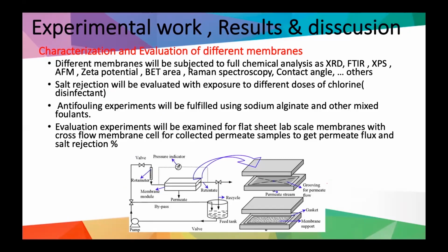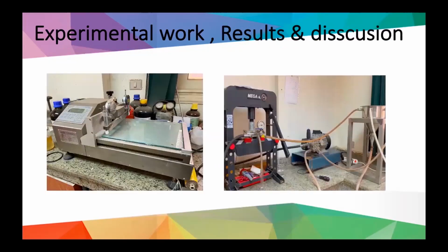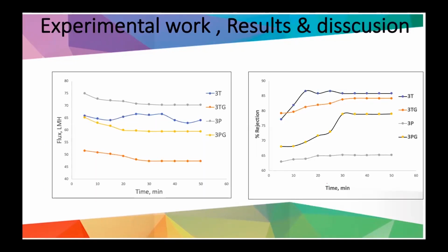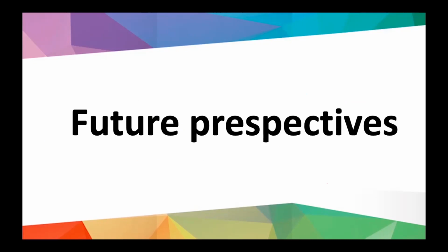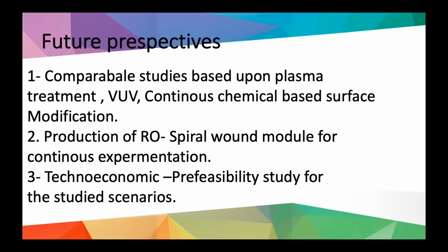Here in our study, we are using a polysaccharide foulant, which is sodium alginate, coupled with other organic and inorganic foulants. This is a part of our lab equipment, which is used for measuring the performance and for casting the membranes. Here clearly, also, is the increase in the percentage rejection by the effect of the blending technique and the thin film composite. Finally, I want to compare our studies with the plasma treatments, the vacuum UV, and the continuous